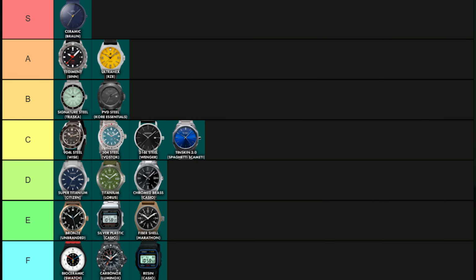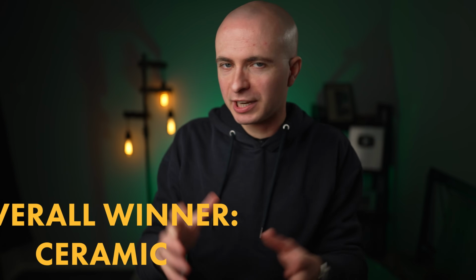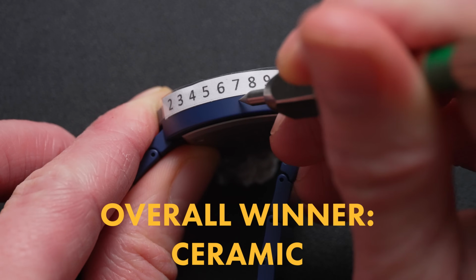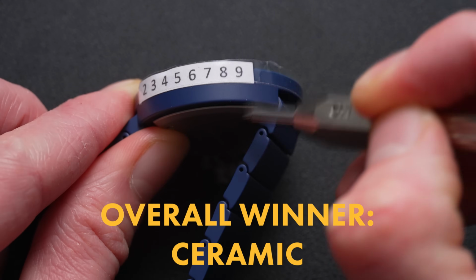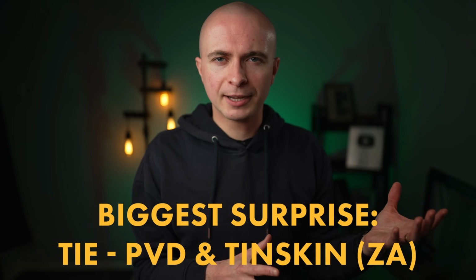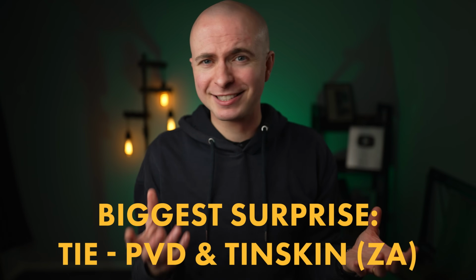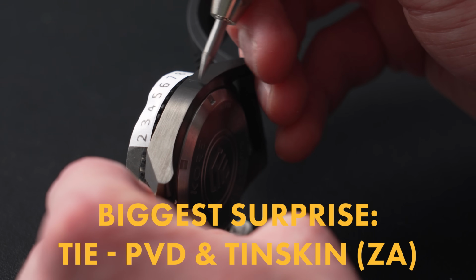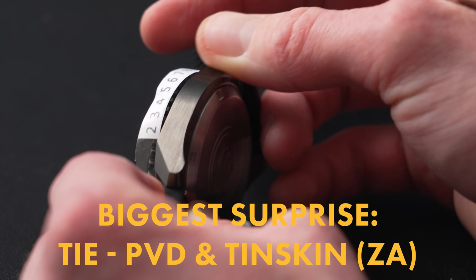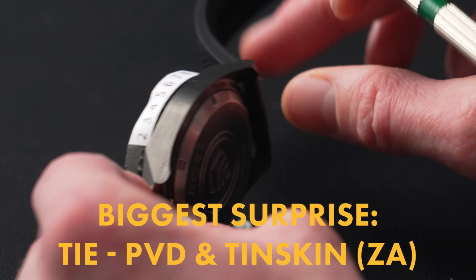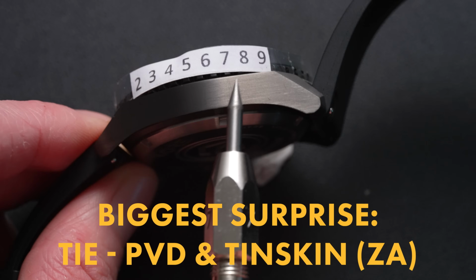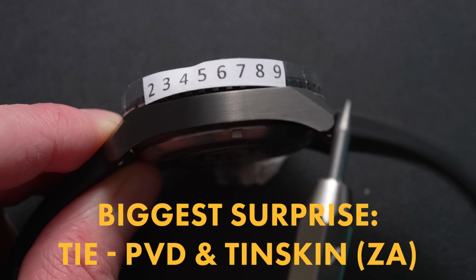It turns out that unlike our crystal scratch test, quite a few of these proprietary materials actually perform better than the basic untreated ones. As for awards, the clear winner was ceramic. That one was near impervious to all the picks. I think the biggest surprise must be either the PVD or, ironically, the Spaghetti Scameti TinSkin. I always knew that PVD supposedly improved durability to some degree, but I was always under the impression that it was more for aesthetics than anything else, so I'm pleasantly surprised it did so well.